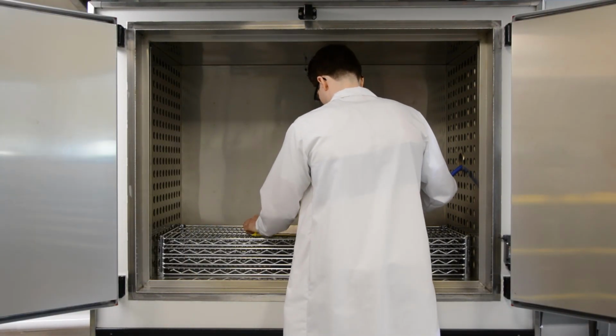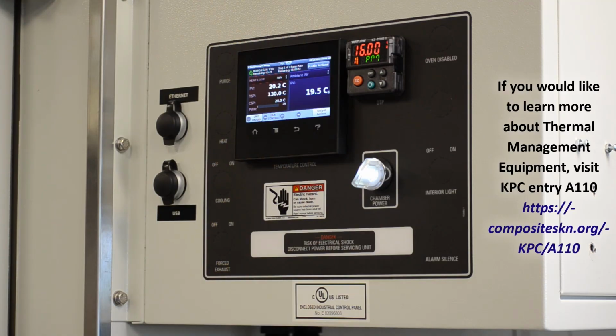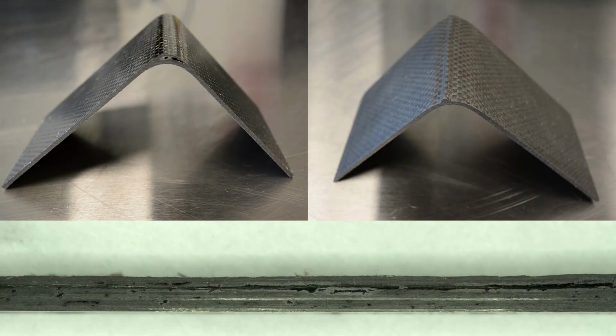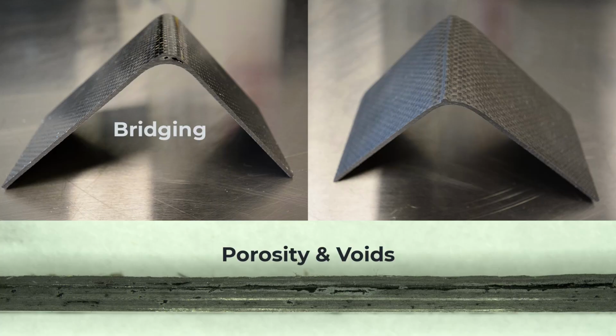The heated cure cycle temperature is tightly controlled to prevent under or overcuring the part and to ensure good resin saturation of the fibers. Depending on part geometry and layup procedures, some common Prepreg defects include porosity and voids, bridging and corner thinning, fiber wrinkling, and fiber waviness. In this video, we will cover the relationship between material deposition procedures and part defects.